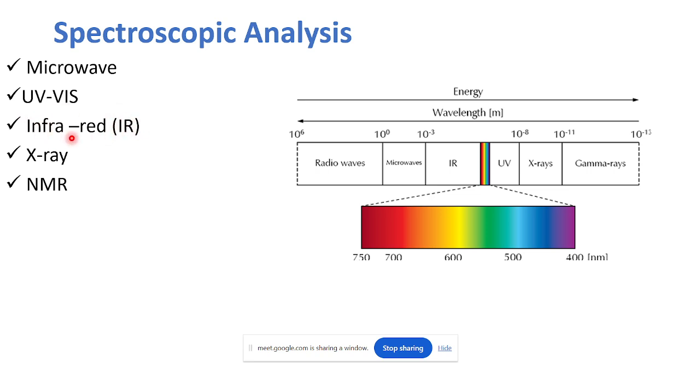Infrared, this is also one kind of structural analysis to probe what the different functional groups are that are present in your material. For example, if you have an NBR type rubbery material, acrylonitrile butadiene rubber, the presence of the C triple bond N group, that is the nitrile group, if it is there, from infrared you will get a peak around 2000 to 2200 centimeter inverse. From there, you can say, okay, there may be presence of the nitrile group.